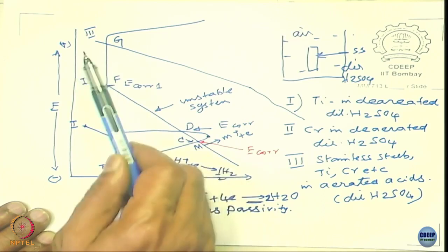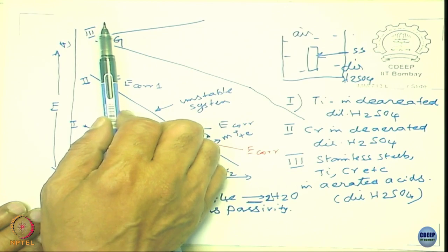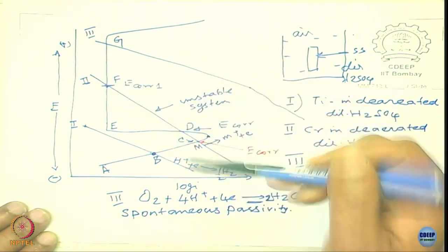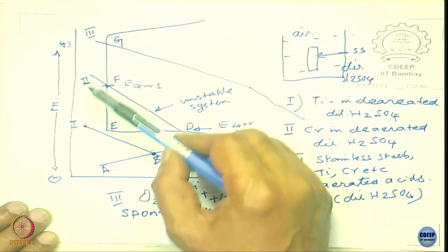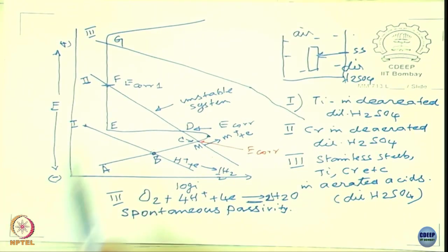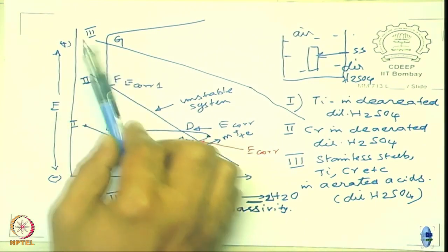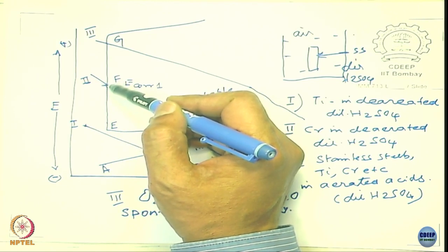This also would depend upon the passive current density. For example, if the passive current density is a little higher, you will get these uncertainties much more, much more can happen. So, the IP value is equally important. We will see this subsequently. If you lower the IP value, the oxidizing agent required to maintain the passivity is very low. So, you will find that once you reach this state, this state becomes quite stable.